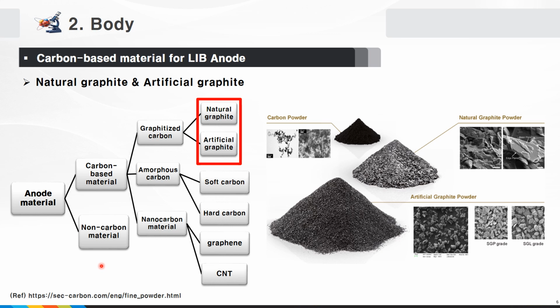Crystalline graphite material contains lithium ions in the graphite layer plane by intercalation, but amorphous carbon material can store lithium ions on the front and back side of nanopores that meet certain conditions among pores generated by repeated carbon layers. First, I will explain the graphite system. Graphite largely consists of natural graphite that is produced and mined in nature, and artificial graphite that is manufactured by heat treating coal-based and petroleum-based pitch above 2,500 degrees.